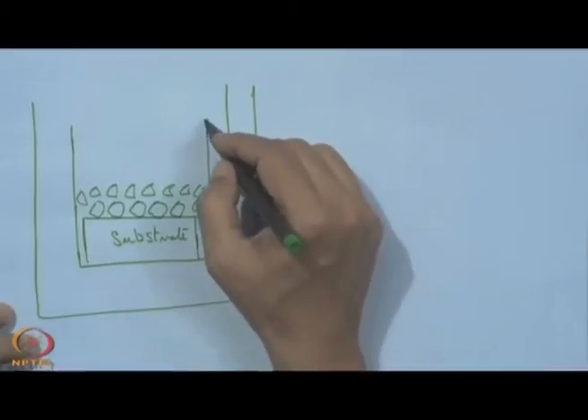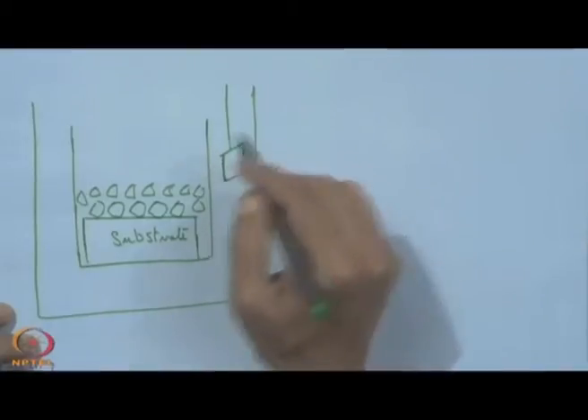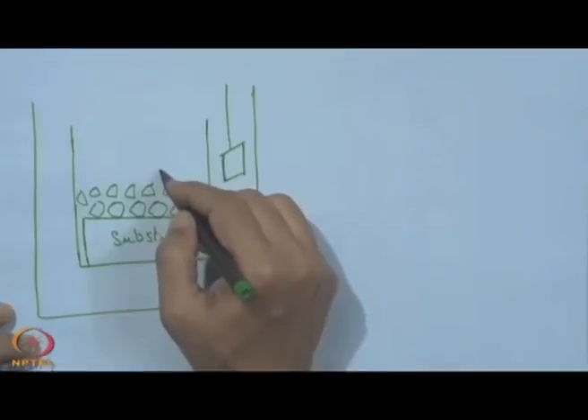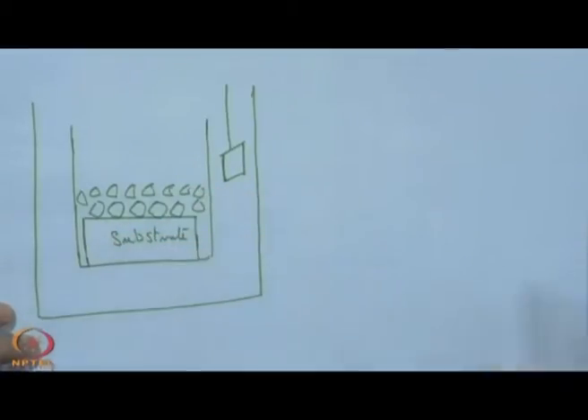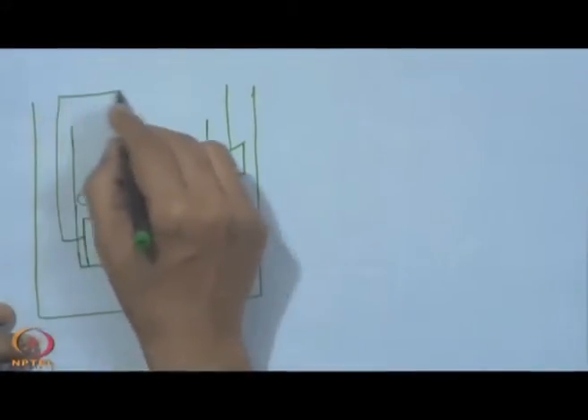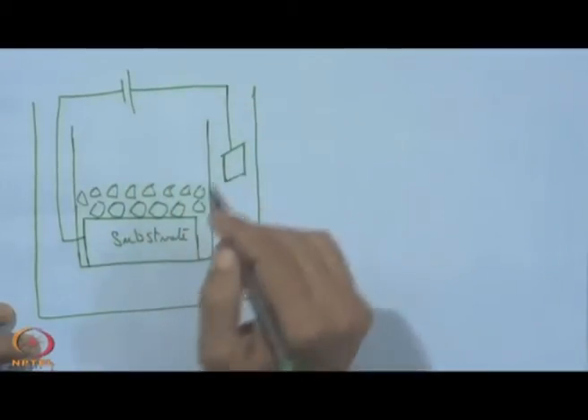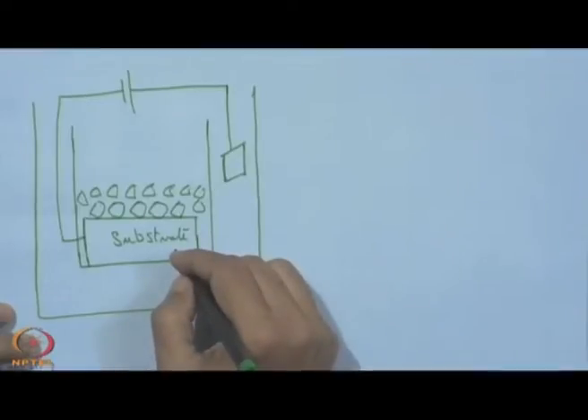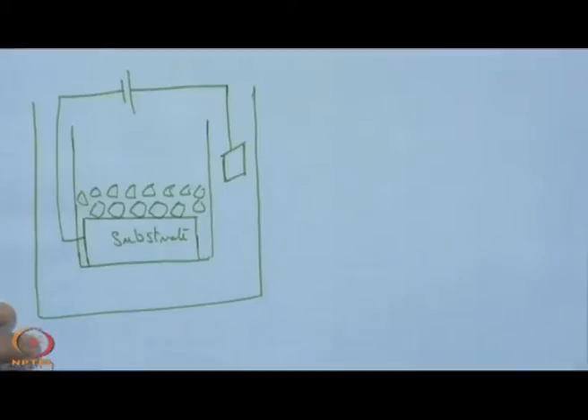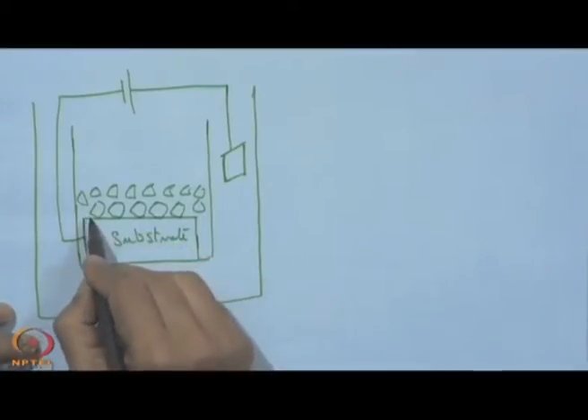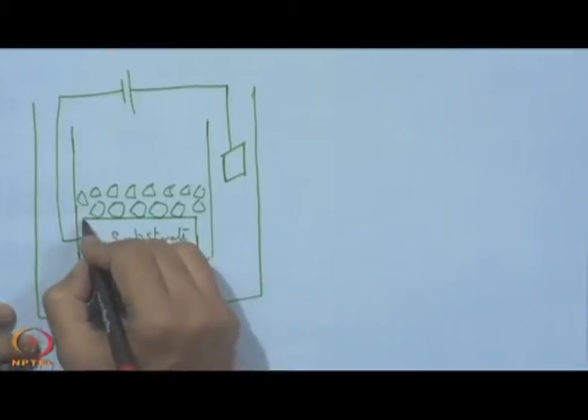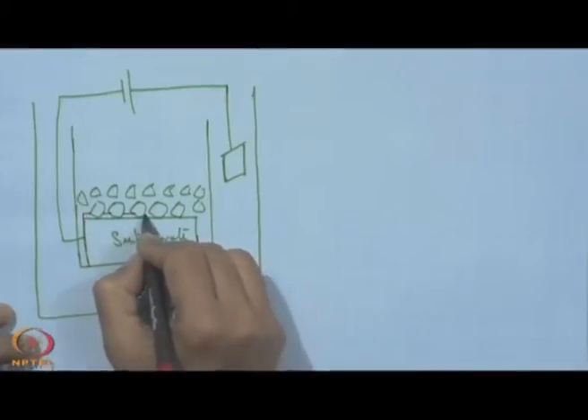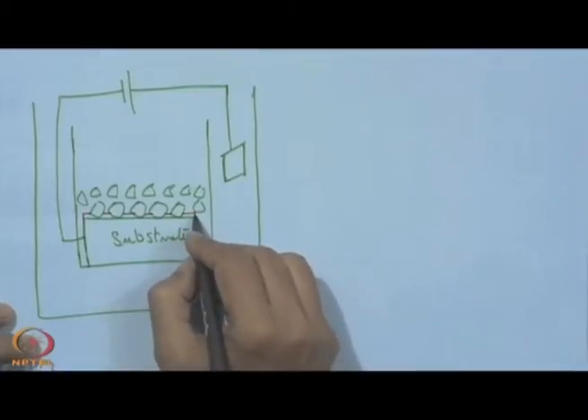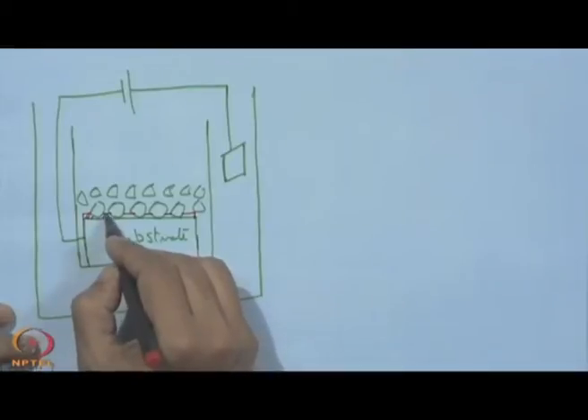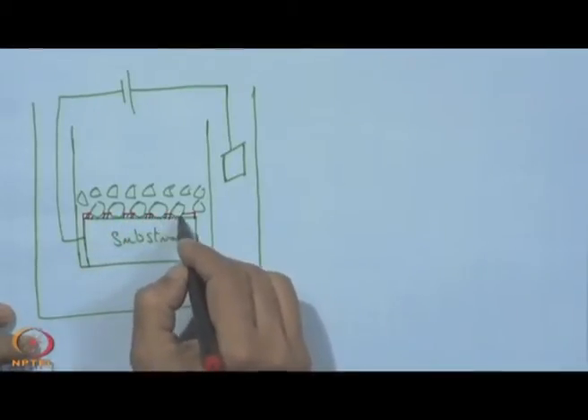So, what is going to happen in this case is that this material with this electrolytic solution is going to deposit on this surface. So, here we see just one cathode and this is going to be the anode, this is the anode plate and that is the cathode substrate. And here what is going to happen is that around the layer of the grit which is touching this top surface of the substrate, wherever we have the space, there will begin the deposition of this electroplated material or galvanic material like this.